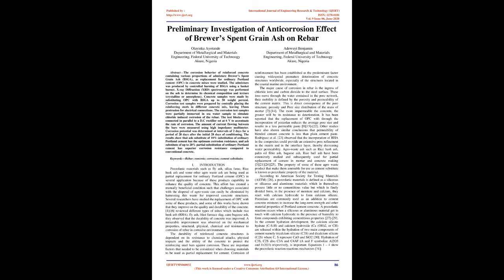Concrete samples were made by substituting OPC with BSGA up to 50 weight%. Corrosion test samples were prepared by centrally placing the reinforcing steels in different concrete mix, leaving 15 mm protrusion for electrical connections. The corrosion test samples were partially immersed in seawater sample to simulate chloride-induced corrosion of the rebar.